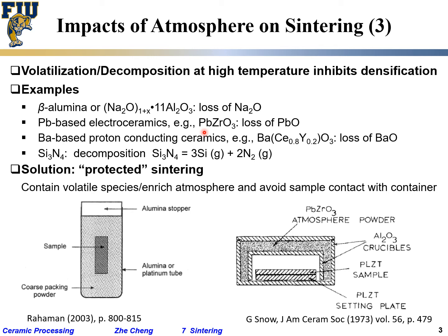And people find that if you sinter this in open air, if the temperature is high, it doesn't sinter very well because over time the lead oxide continues to evaporate, continues to go away from your sample and into some other, colder section of your furnace. It just leaves your sample. So for those, it can be problematic.